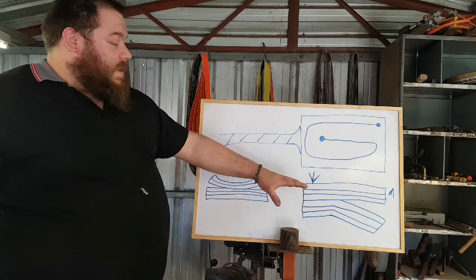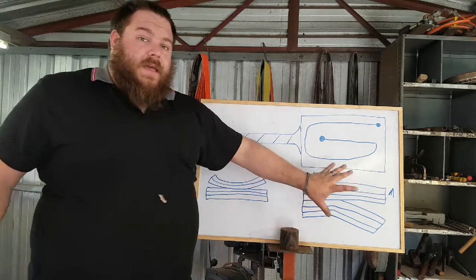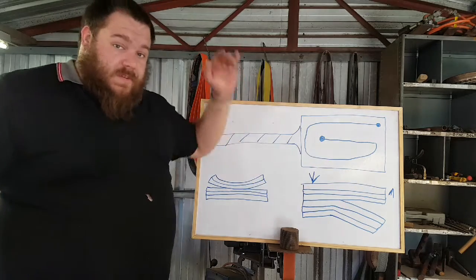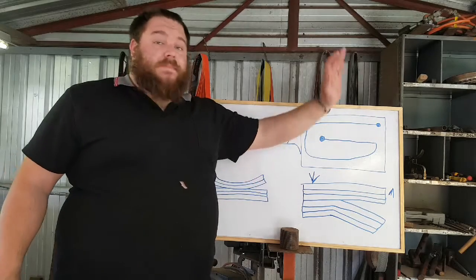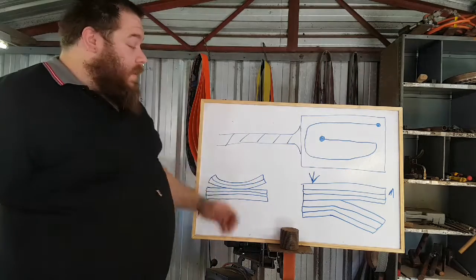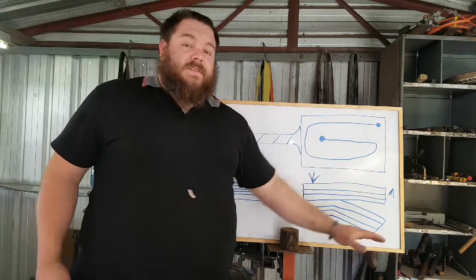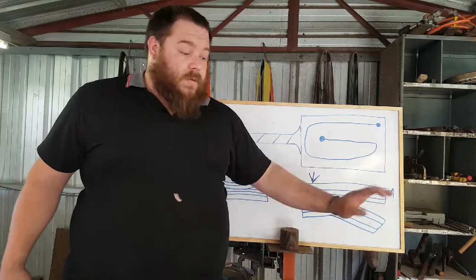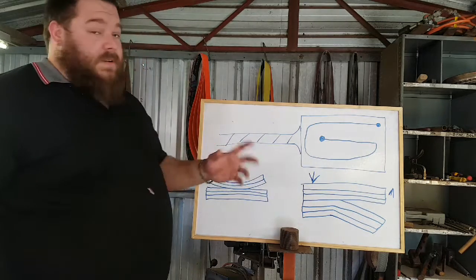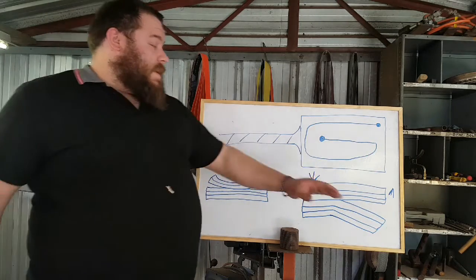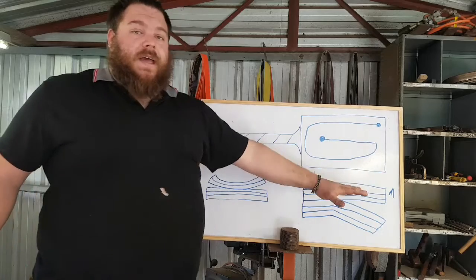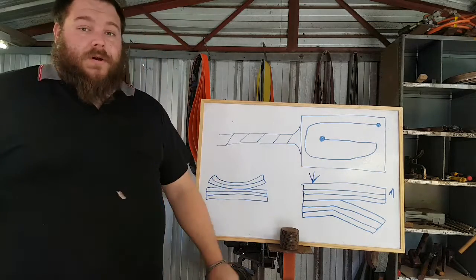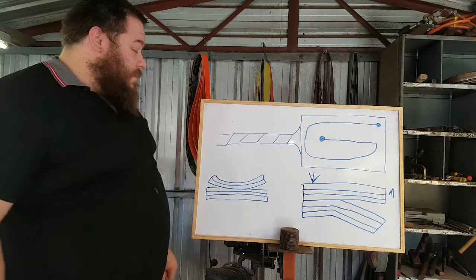So, basically, because he hit way too hard, and not with a pressing force, but more with a striking force, it caused that really big shear, and that busted the weld. And unfortunately, we didn't manage to salvage the top part of our billet. We have welded the bottom part of the billet, and that'll still be part of this series, but once that weld failed, scale developed in there, and no matter how much borax we put in there, we weren't going to consolidate that back into the piece.